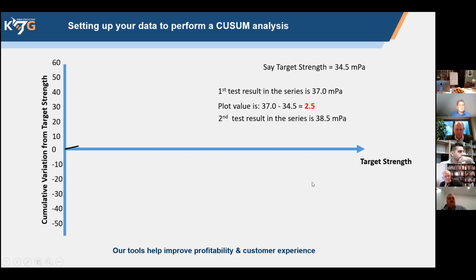The second test result says 38.5 megapascals. And the plot value would be 38.5 minus the target strength again, plus the previous CUSUM value of 2.5, giving us 6.5. It's that simple, that rudimentary. But you can start to see that as we have 2 results that were greater than the target strength, the line is moving in a positive direction. Remembering the target is to keep it at 0.